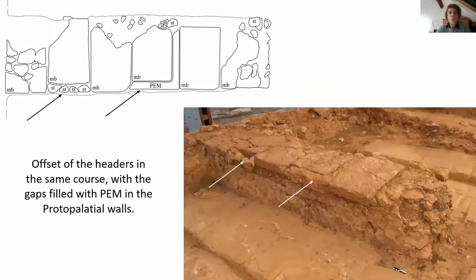In the Protopalatial walls of the eastern magazines, the bricks are laid in header bond, but the specimens are offset horizontally within the same course. The gaps thus created are filled with small stones and mudbrick fragments set in PEM. This bricklaying made it possible to create a wall wider than the brick's length, and at the same time, the plastic nature of the PEM provided a cohesive link between the components within each course.